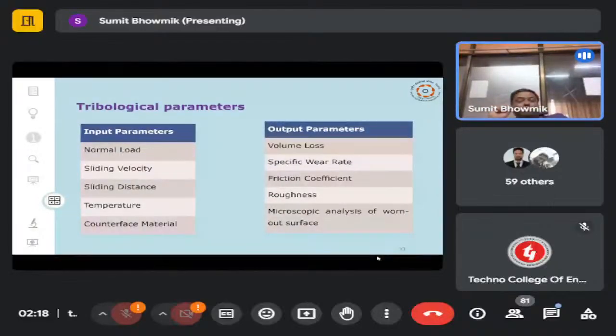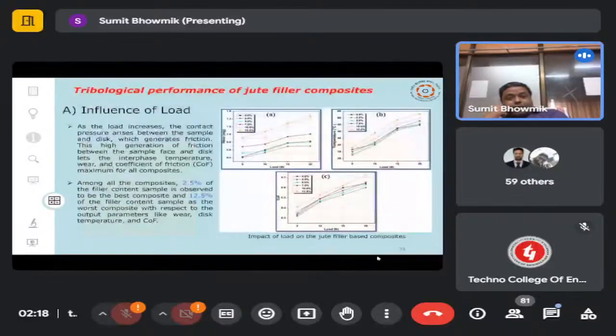And from there what we will get is the volume loss due to that friction, how much material has lost its volume, then how much wear rate, the friction coefficient, and the roughness of the surface. Okay, and of course after that microstructural analysis has to be considered. Now here jute filler has been considered in most of the cases. Why not wood, banana, or some other? That is also done, but here I am representing mostly jute and bamboo.